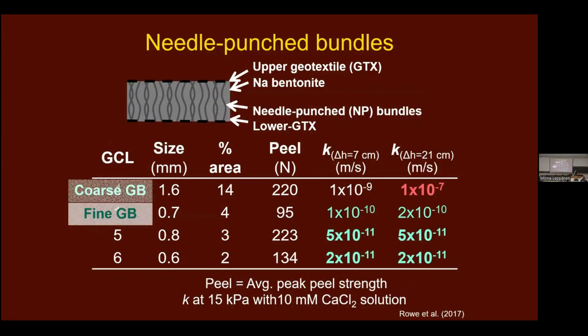Now, let's throw a powdered bentonite into the mix. So here we've got the coarse one that we looked at before, 1 times 10 to the minus 7, fine at 2 times 10 to the minus 10, and 2 GCLs with powdered bentonite, 5 times 10 to the minus 11, 2 times 10 to the minus 11. You can see that there is a difference in performance because of the history and the nature of the GCL.